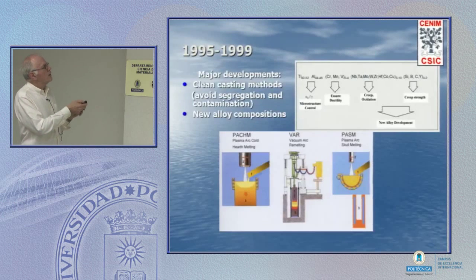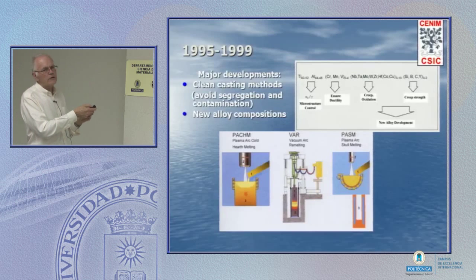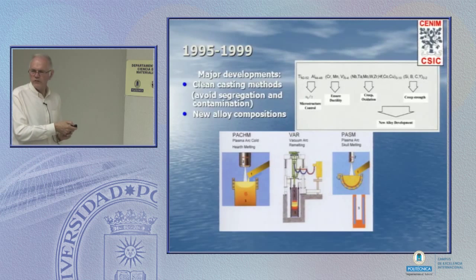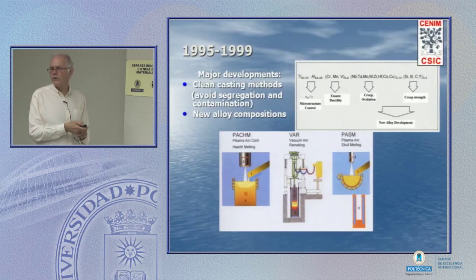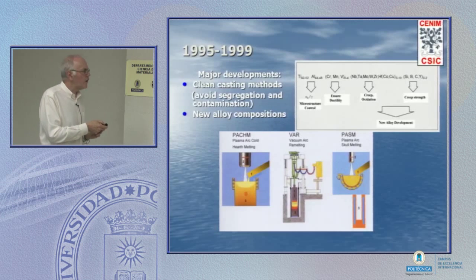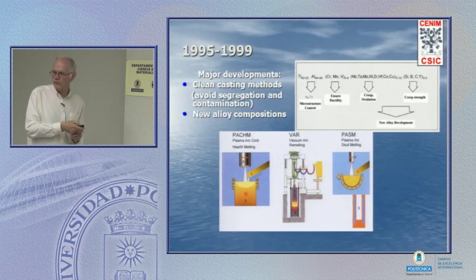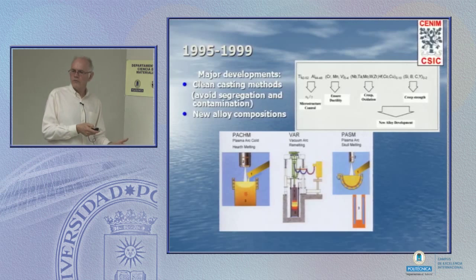Now, what's happened, this is maybe 1990 to 2010. There have been changes of processing technique and changes of alloy composition. Titanium plus aluminium is very, very reactive when you heat it up towards the melting point. It reacts with the crucible if you're trying to melt it, it reacts with the environment. So there's been lots of development of plasma, cold hearth, under vacuum. There's been the development of techniques, very much as you have for titanium alloys, but going a little bit further.